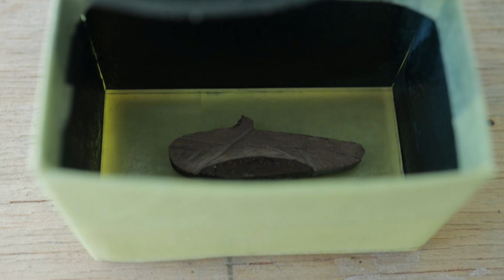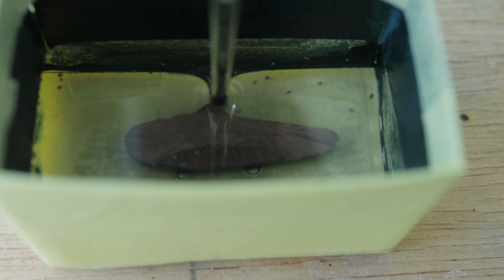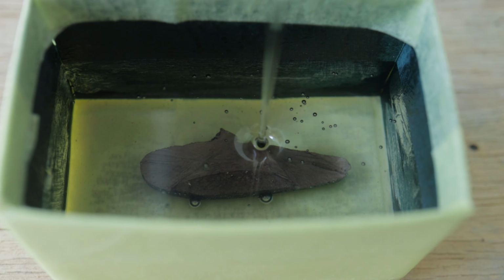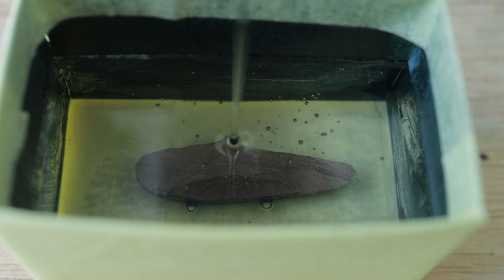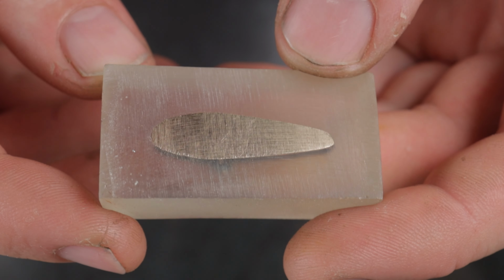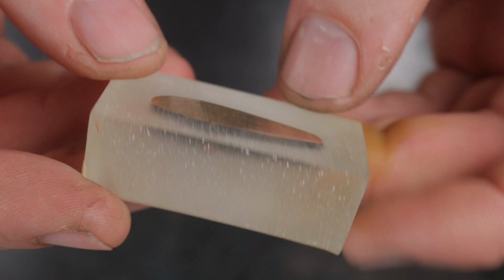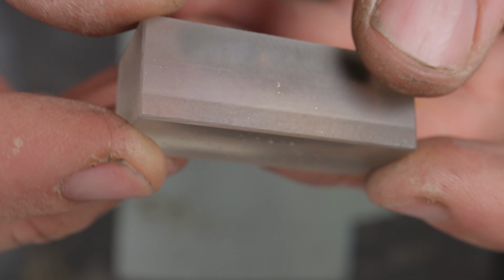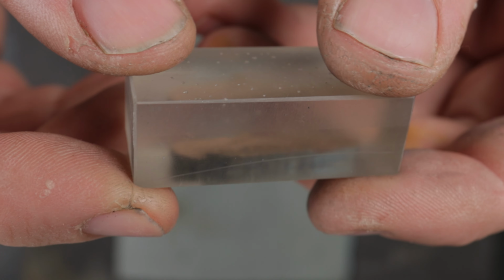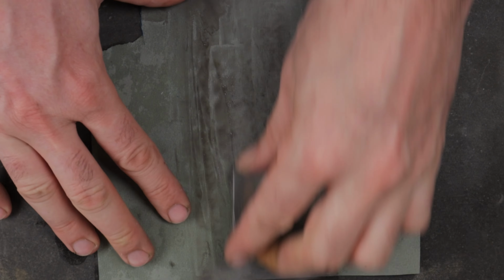First, I need to make the piece manageable. I chose to encase the metal in epoxy resin. After curing, I roughly cut the sample and squared it on a milling machine. Now it's time for grinding and polishing.